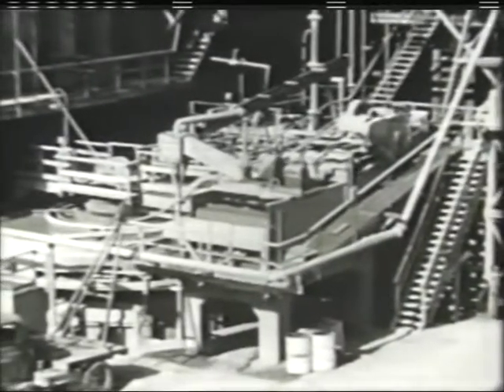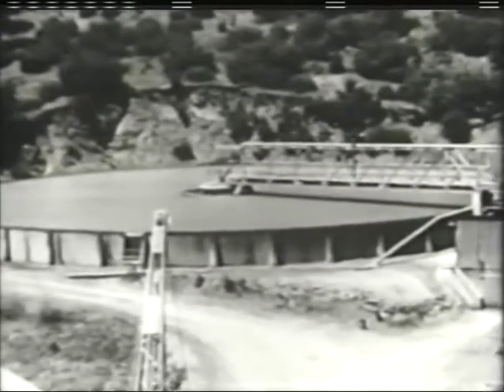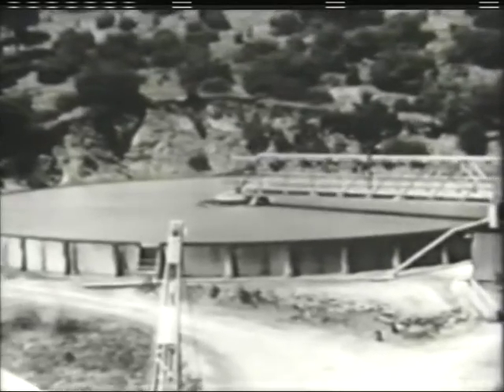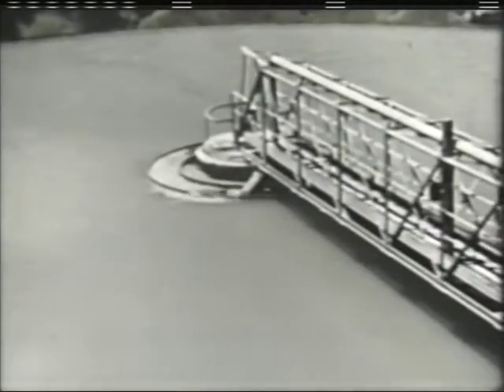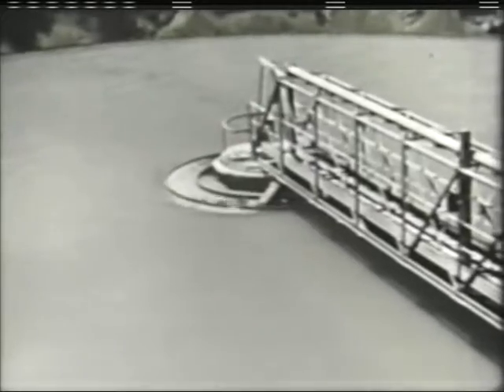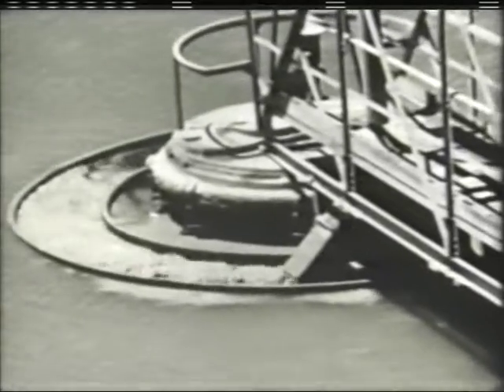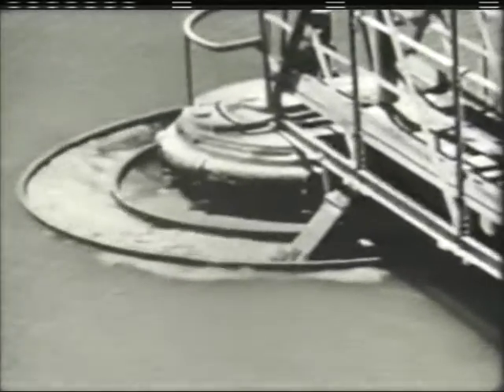The finely ground rock and water, known as slurry, pours over the lip of the bowl classifier. At this point, the slurry contains 85% water and 15% ground rock. Since this is far too watery to feed into a kiln, the mixture is first sent into thickeners. In these 150-foot diameter tanks, the solid material settles. The mixture is then circulated by pumps until the slurry that comes out is 65% solids and 35% water.